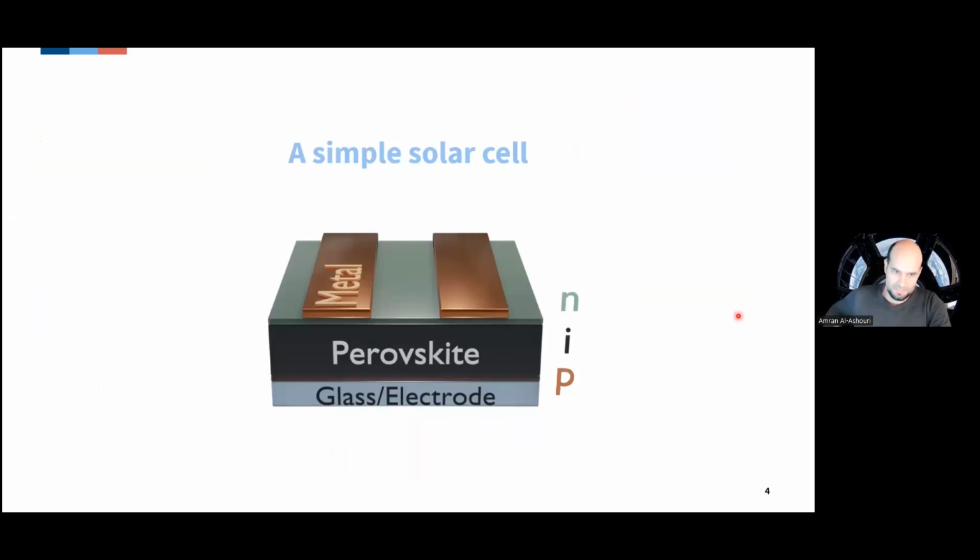So we start with a simple solar cell. We like these PIN solar cells in our group because they're low temperature processable, and in principle they're rather simple. They're close to the theoretical simplicity of a heterojunction solar cell. So we have a perovskite sandwich in between, and ideally you want to choose a perovskite composition that is quite reproducible and robust to make. And then when you just take care of contaminations in your powders, it's usually no problem.